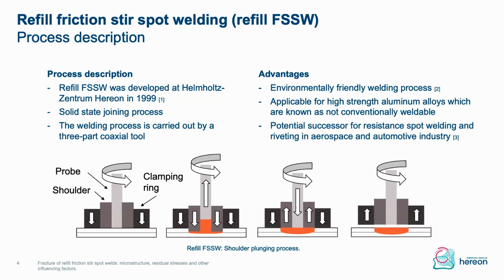Before the actual weld starts, the weld object is getting clamped by applying a clamping force. And afterwards, the probe and the shoulder start to rotate. While in this case, the shoulder plunges into the material, the pin accommodates the displaced material. In the refilling stage, it's the opposite. So the pin pushes the material back while the shoulder gets pulled out of the material. At the end, the clamping force is taken away, and so the process ends with that step.